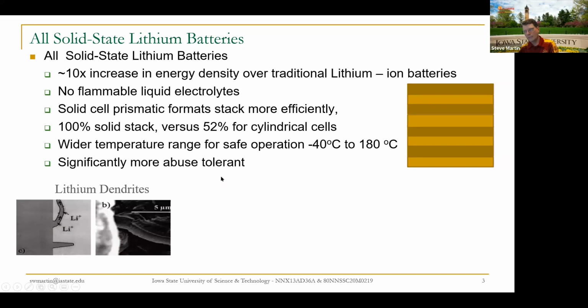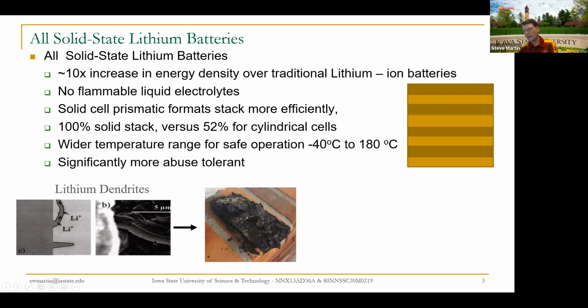A pretty common source of that fire is when the lithium doesn't get tucked in and safely intercalated by the graphite, and it stays out on the edge. Here's a little cartoon by Mark Duff. And what happens is the lithium ion, instead of getting tucked inside and intercalated into the graphite, it precipitates on the outside, forms these little wires, these little dendrites, and here's an actual SEM of a dendrite. And they grow across the battery and short the electrolyte out. The distance is only about 30 microns.